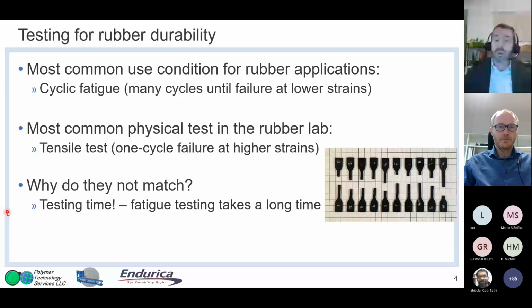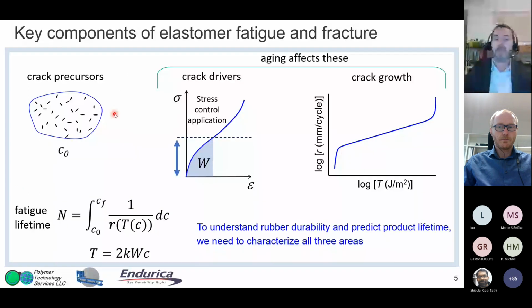I'm mainly going to talk about crack growth today because the fatigue threshold is in fact related to this portion of the crack growth curve. However, if we're going to understand elastomer fatigue and fracture generally, I've broken it down into different areas: crack precursors in the material, which could be undispersed filler, contaminants, raw materials, and the like; what's driving the crack, the stress, strain, and strain energy density that's pushing on the cracks to grow; and how fast the cracks grow, which is dictated by this crack growth curve that you'll see a lot of discussion about today. So again, I'm going to focus on this one component, but keep in mind this bigger picture, and we need to understand all of these areas in order to understand rubber durability and predict product lifetime.